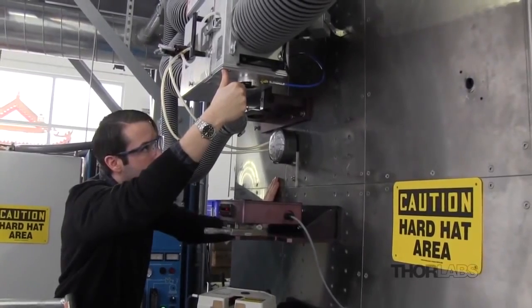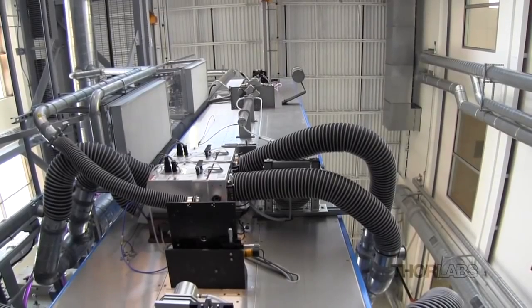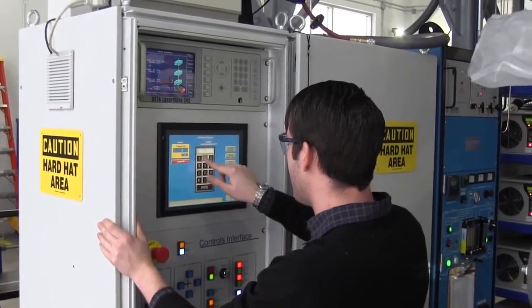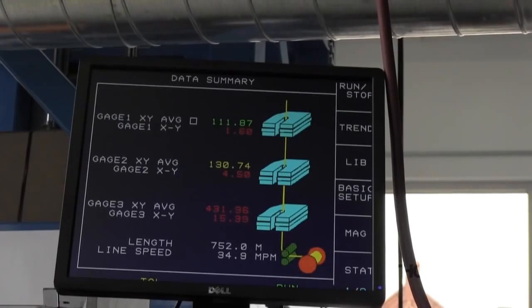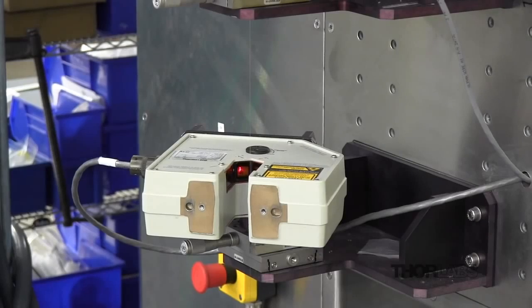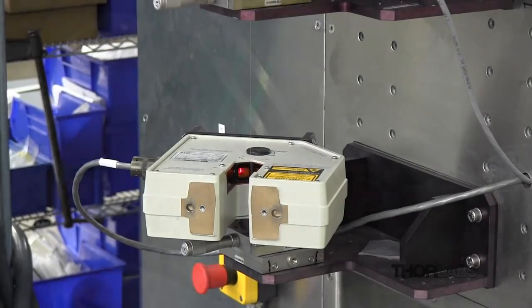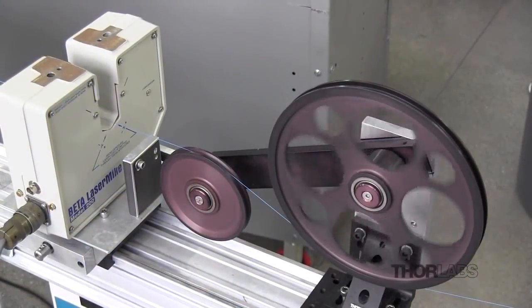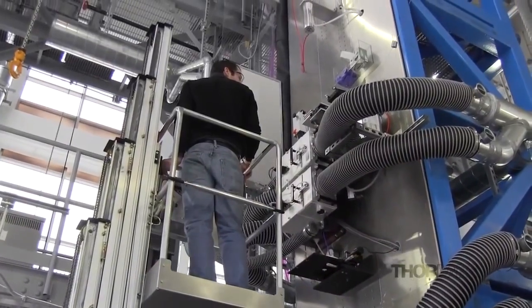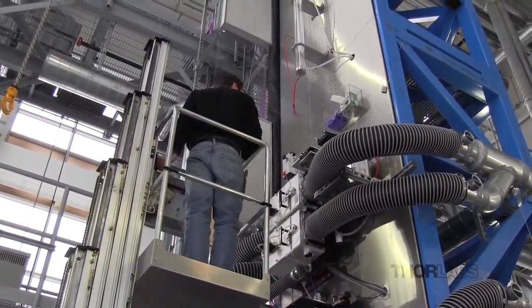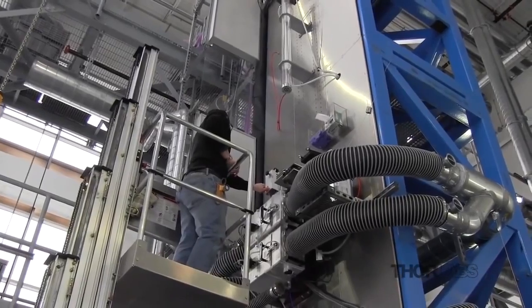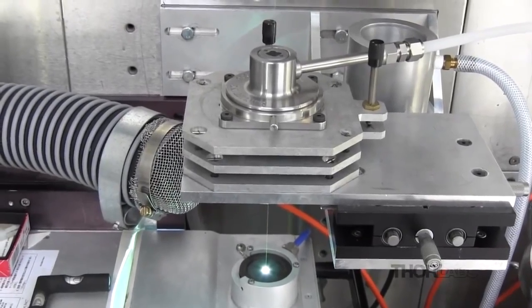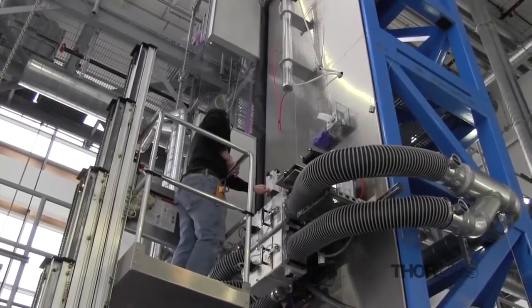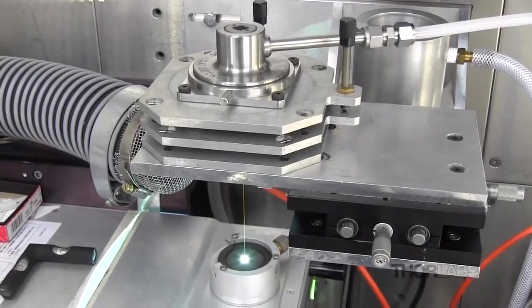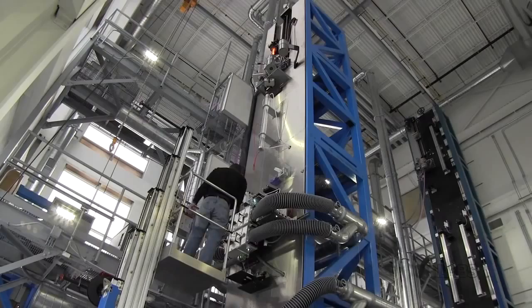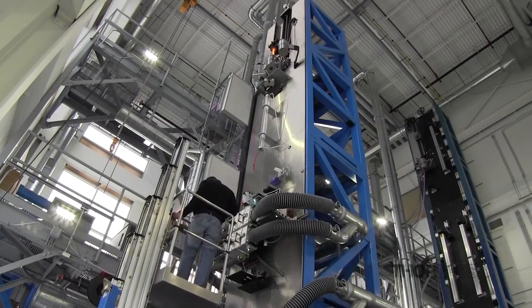The fiber is closely monitored as it makes the 36-foot journey from the top of the tower to the capstan below. 3 gauges provide real-time diameter measurements to computers controlling both the speed of the top feed and the capstan. These speeds are constantly being adjusted to ensure a consistent diameter throughout the length of the fiber. Our engineers also monitor the location of the fiber as it travels through the many devices and make adjustments when necessary. It is important that the fiber is perfectly centered because any rubbing will negatively affect the quality of the end product.